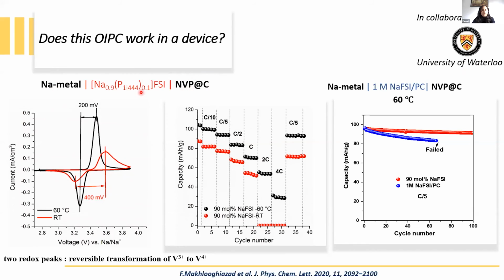So we fabricated a sodium cell based on one of our organic ionic plastic crystals mixed with sodium salt that we well characterized. And we did cyclic voltammetry of the cell at two different temperatures, room temperature and at high temperature, 60 degrees. And we saw two redox peaks that are because of the reversible transformation of vanadium 3 to vanadium 4. And interestingly, we saw that the potential interval between oxidation and reduction peak is less at higher temperature. That shows the lower polarization potential at higher temperature.